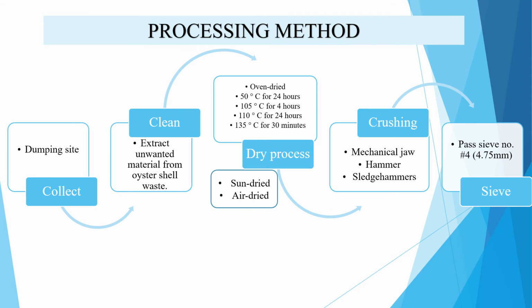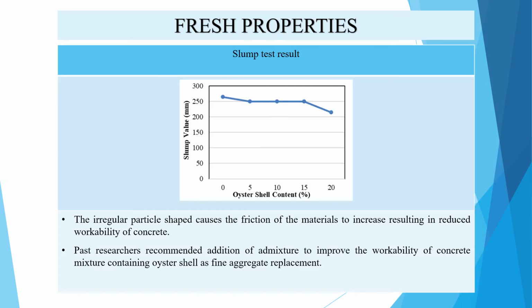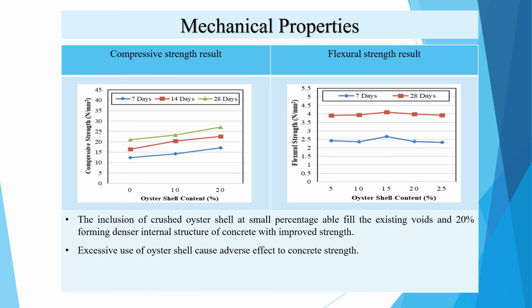This is the processing method to produce oyster shell as fine aggregate based on past research. Based on previous studies, the result of the slump test for oyster shell as fine aggregate keeps decreasing. Past researchers state that the irregular particle shape causes the friction of the material to increase, resulting in reduced workability of concrete. And past researchers recommend the addition of admixture to improve the workability of concrete mixtures containing oyster shell as fine aggregate replacement. Oyster shell as fine aggregate shows a positive result in strength.